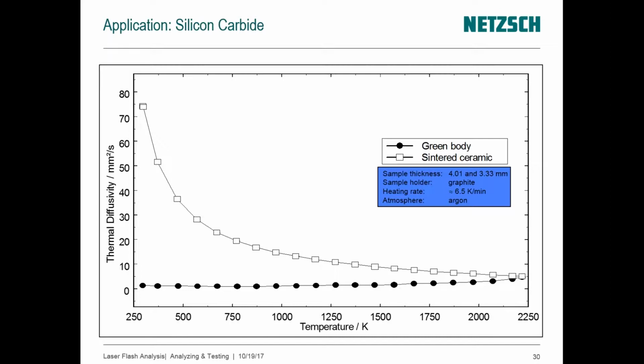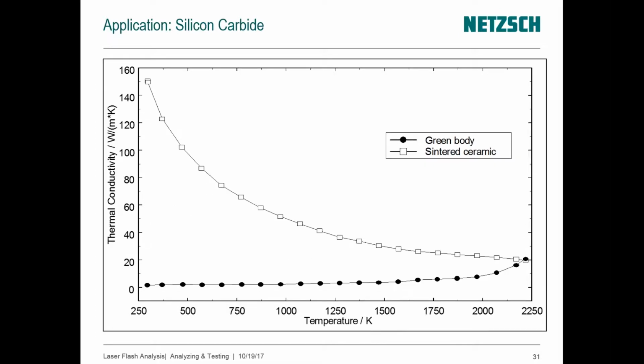Now, for a different type of ceramic, of silicon carbide, in that case, the green body has been a little bit modified with other components. If you remember the first slide and now the second slide, you see that above 2000 degrees, the behavior changes a little bit. And because of probably an additive added to the green body, or the grain size of the silicon carbide particles themselves. In any case, we see that by the time we cool down again, we're measuring going up and going down and cooling down, and you see that in this particular instance, compared to the previous slide, in the previous case, you see that the overall diffusivity and conductivity are much higher.